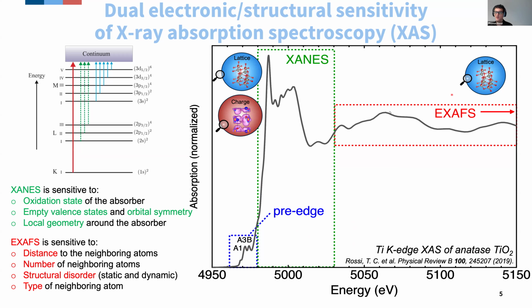There is one part here, very popular, the EXAFS, that's well above the ionization threshold. You have these oscillations that you can Fourier transform to get pair distribution functions, for instance. So this is a part of the spectrum that's uniquely sensitive to the lattice. In the XANES, however, when you get closer to the ionization threshold, you start to have sensitivity to both the lattice and the charge degrees of freedom. And it makes the interpretation of spectra much more complicated.